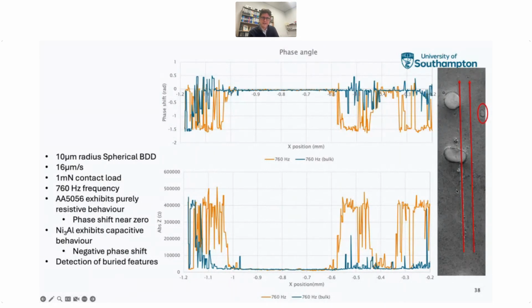lines here. So on the left, you have a trace that penetrates over the top of these two Ni3Al particles, and then we've done the trace again just in the matrix away from these particles. And what we have is the blue line is the response from the right-hand line, just over the bulk, if you like, the matrix, and then the orange line is when we've gone over the particles. And you can see on the right-hand side here, as we're getting to a later point in the trace, we're getting again a drop in this phase angle and an increase in the absolute value of the Z, the impedance, and so this can determine that phase change there.